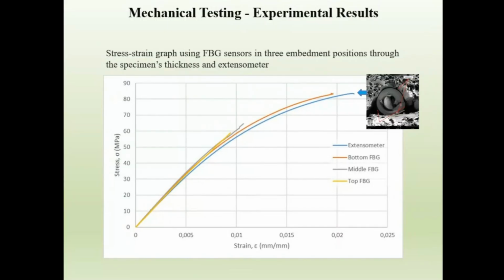So if we convert that to stress strain curves, you can see here that, despite maybe what we were expecting, some significant differences especially for the mechanical response coming from the fiber optic sensor that is closer to the bottom surface, that means the first layer, which is experiencing all the thermal gradients developed until the end of the building. We can see that the in situ mechanical response is pretty close, or actually I would say the opposite way, the one that we obtain from the extensometer is very close to the ones that were recorded from the fiber optic sensors.